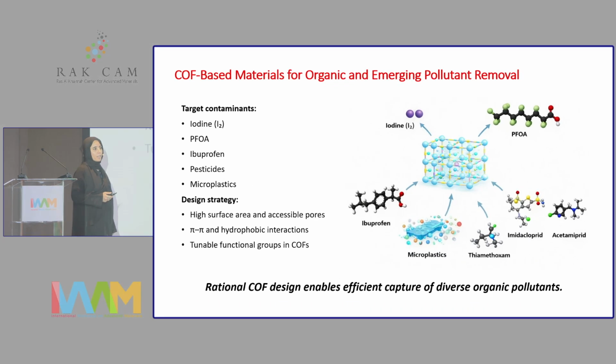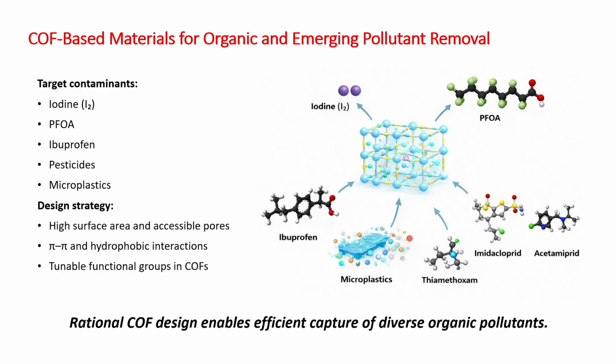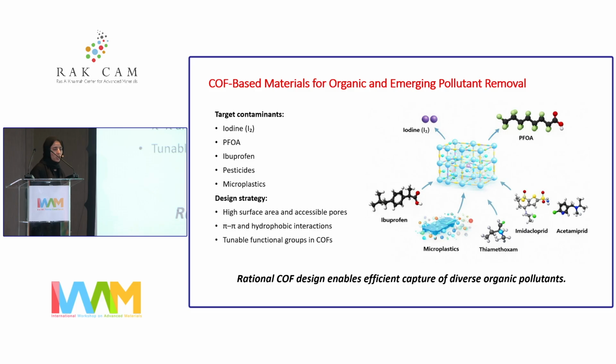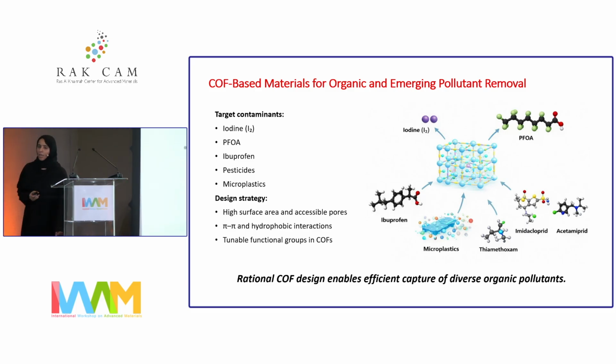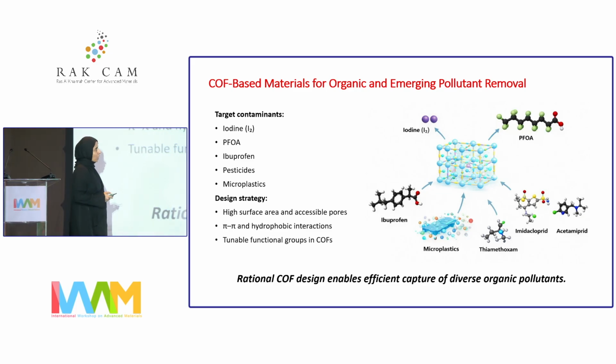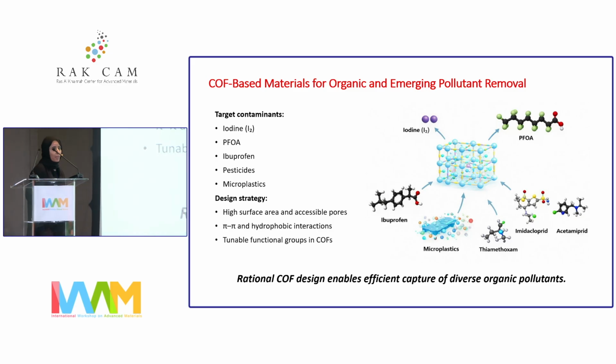Actually, in our lab, we custom synthesize the linkers or the building blocks for the COFs that we use to capture organic or emerging pollutants, such as perfluorooctanoic acid, iodine, pesticides, microplastics, and others. The idea is to custom synthesize the linker in order to have a functional group that will be able to interact with the pollutant to enhance the adsorption capacity. We also keep in consideration other factors, such as high surface area, high porosity, thermal and chemical stability of the COF, in addition to recyclability and selectivity. Today, I will talk about 2 pollutants, which are perfluorooctanoic acid and iodine.